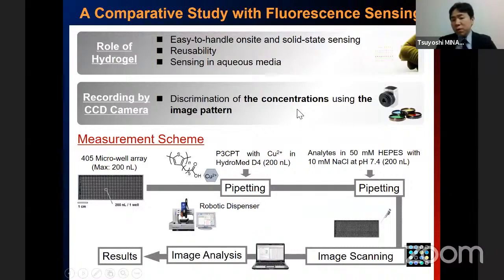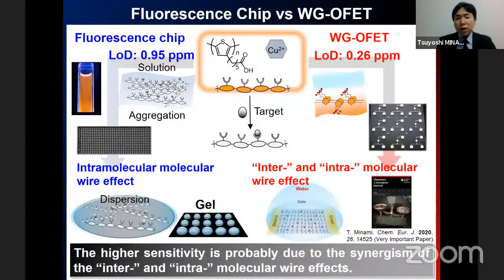And finally, we try to compare the detection ability with fluorescence sensing. To enable on-site detection, we fabricated a glass chip. In that case, we mixed the polymer with the hydrogel on the glass chip, took a photograph of the fluorescence image, and analyzed the detection limit. So here is the result. When we employ fluorescence detection, the limit of detection is 0.95 ppm, while our organic transistor shows 0.26 ppm. Even though we employ the same material, they show different LODs. So the organic transistor is the more sensitive way to detect glyphosate. This is the first example of a comparison between fluorescence and the organic transistor, showing which is the more suitable platform for chemical sensing applications.